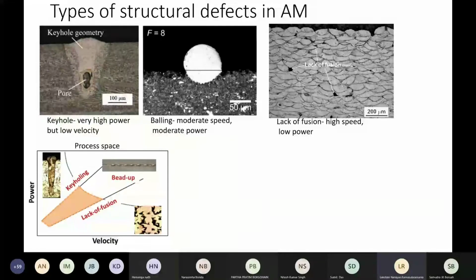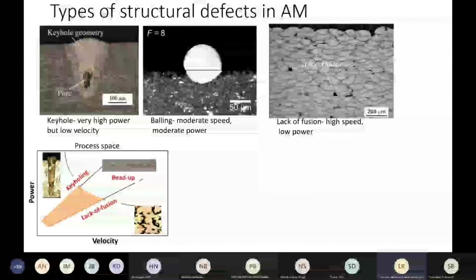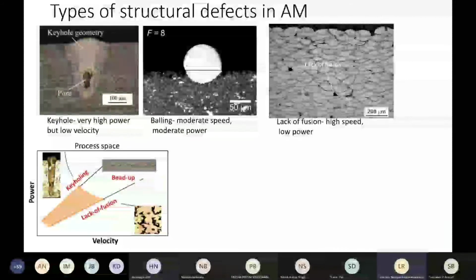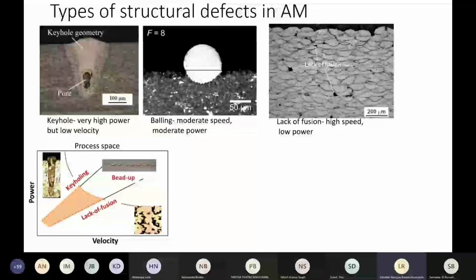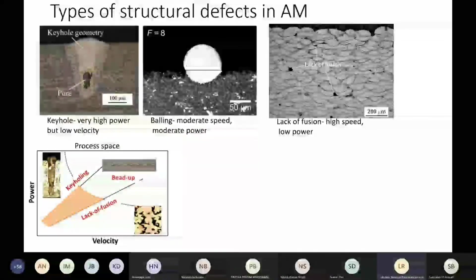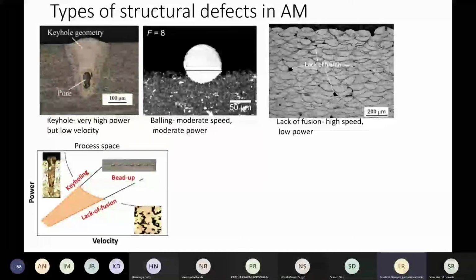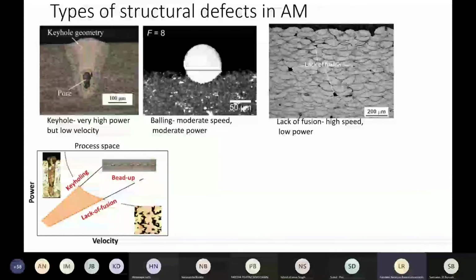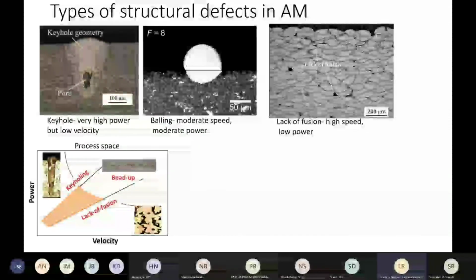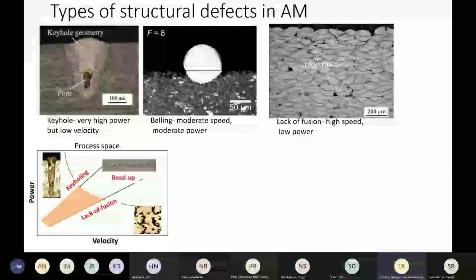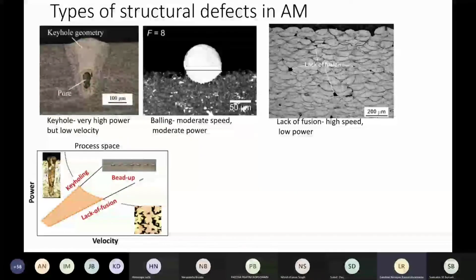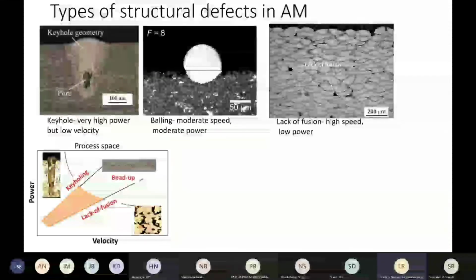And finally, you will have a process space where you can define that at high powers keyholing will occur because the laser has bored through the material. You can see this keyholing has occurred at lower velocities, and at very high velocities and low power, you see that there's lack of fusion. And in between, you can have bead up. So this process space decides where you can do ideal printing. Okay. And you can see that this particular rectangle which has been shown was identified as the ideal space. Unfortunately, even if you do this, you can still not avoid defects completely.